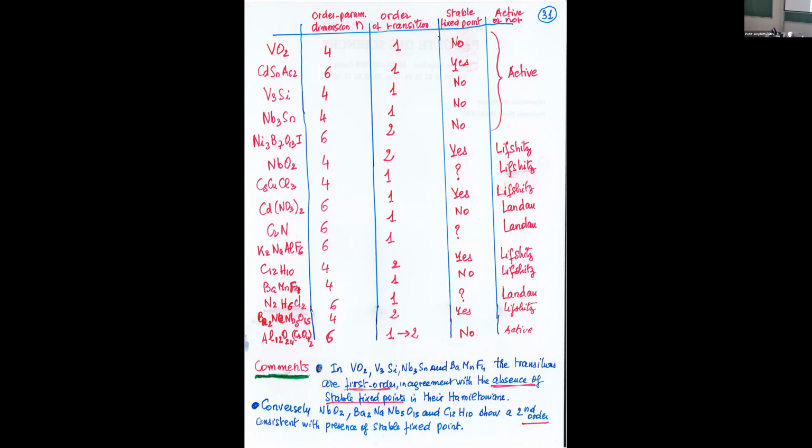Then what theoretically followed? First, the first ones were interpreted by the fact that the Lifshitz condition was not fulfilled. So you had a Lifshitz invariant, okay. Then people found incommensurate phases without a Lifshitz invariant, even in systems where the Lifshitz condition was satisfied. And so they began to invent the concept of Lifshitz-type invariant, something which looks like a Lifshitz invariant but which is not the Lifshitz invariant at a high symmetry point of the Brillouin zone.